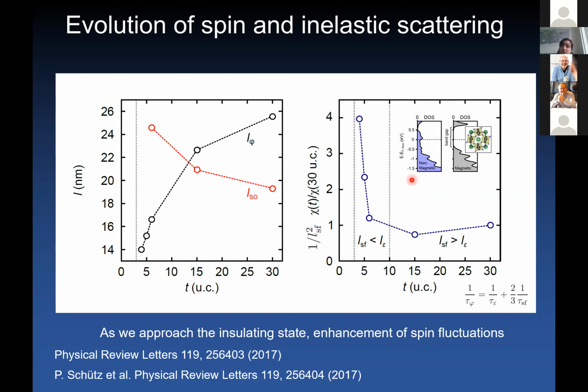So this is consistent with the DFT results, that in order to stabilize the insulating phase, you do need this spin ordering to occur. So as the system starts to form patches of antiferromagnetic order domains, you start to enhance your spin fluctuations.